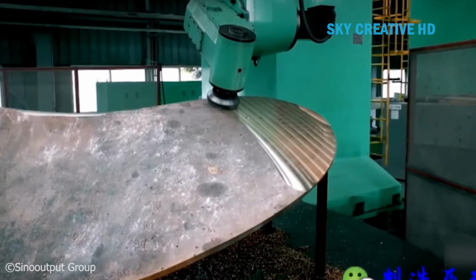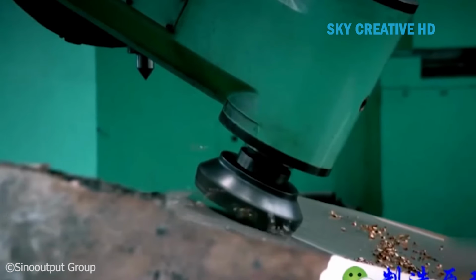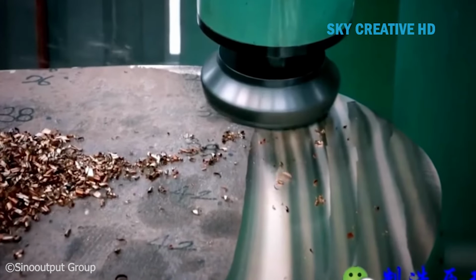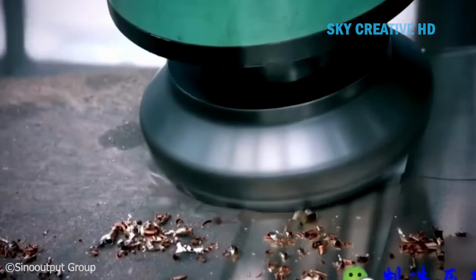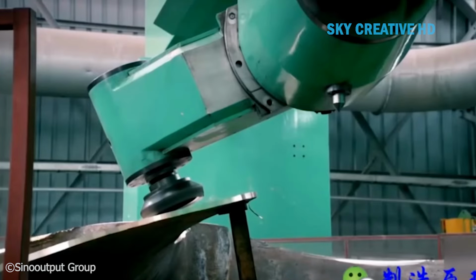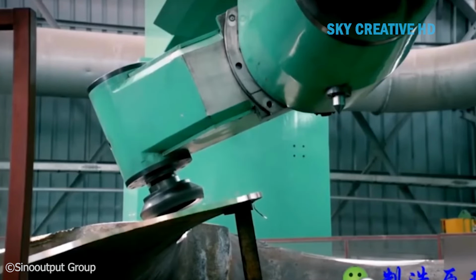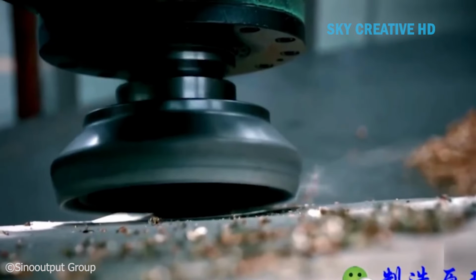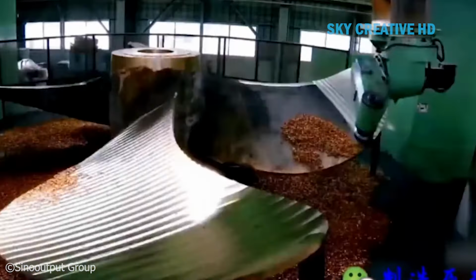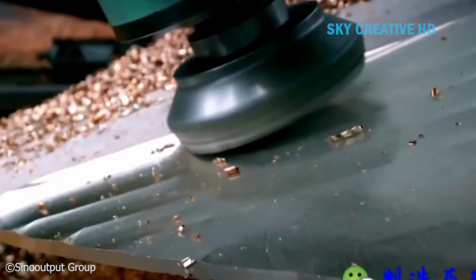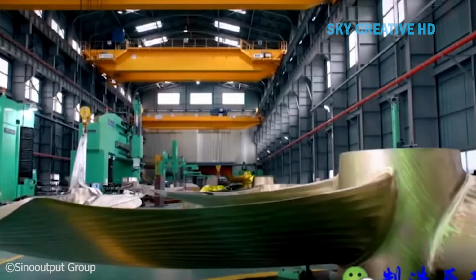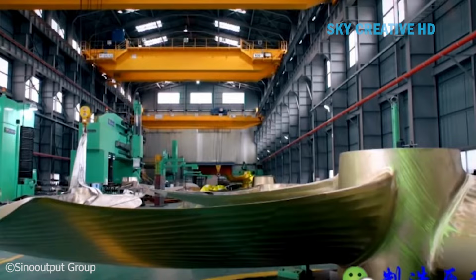Now begins the precision machining phase. CNC 5-axis milling machines, equipped with computer models of the perfect propeller geometry, mill each blade's complex curved surfaces. These curves aren't random. They're based on hydrodynamic calculations, ensuring maximum thrust with minimum cavitation. The blade pitch, thickness, and trailing edge all get machined to tolerances of 0.040 inches.